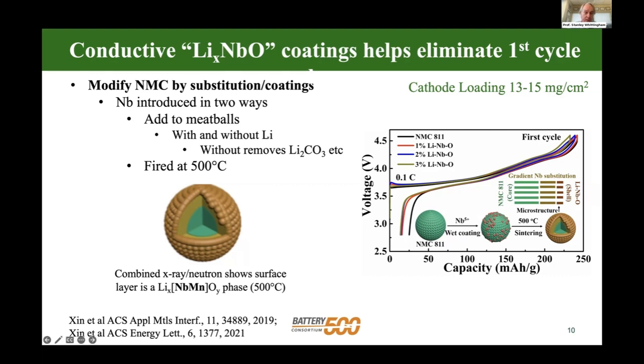But what we found out is, if we take the meatballs, immerse them in the niobium oxide solution, and then heat to 500 degrees centigrade, we get a complete coating on the outside, plus diffusion into the first few nanometers. As the niobium goes in, it kicks some of the manganese out. So this surface film is a complex lithium niobium manganese oxide phase, and this is protecting the surface.